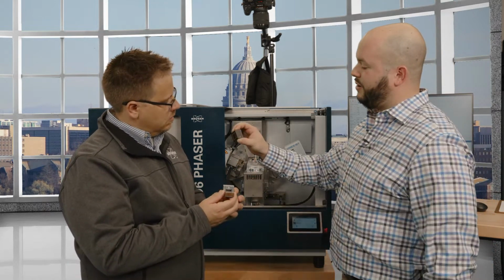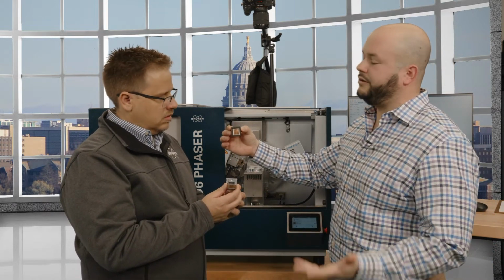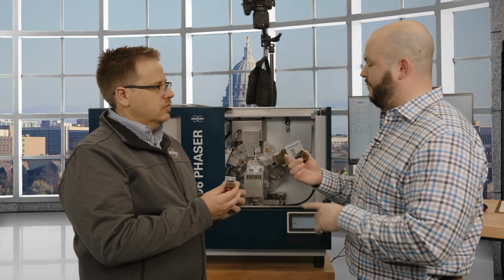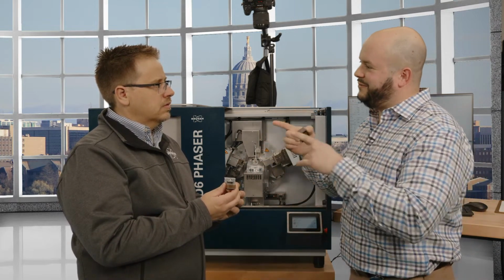And this is just a 2.5 degree axial Soller that you would use for 1D measurements like powder diffraction, eliminating those kind of low angle tails on the peaks at low angles. Because again, you have the superimposition of the Debye rings, right?